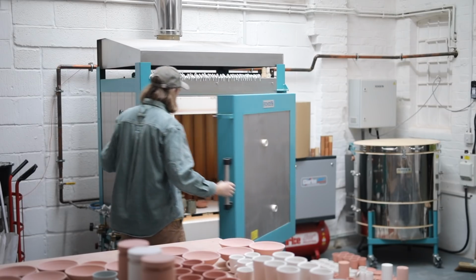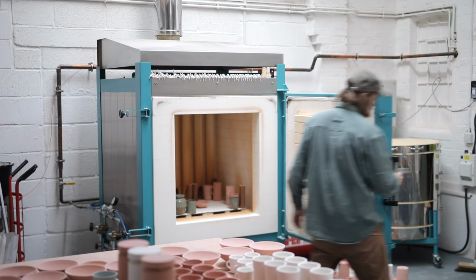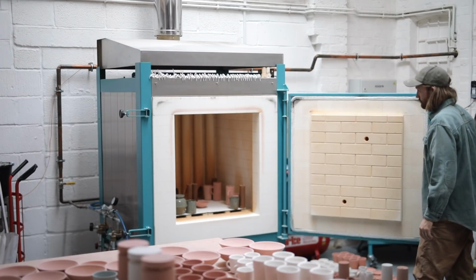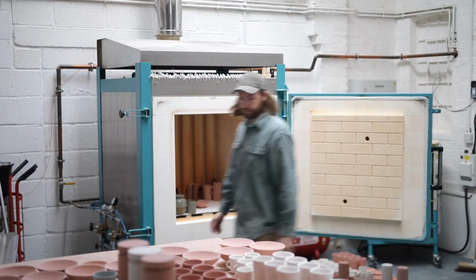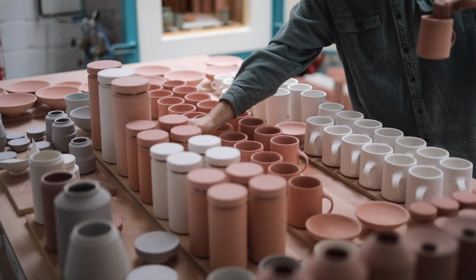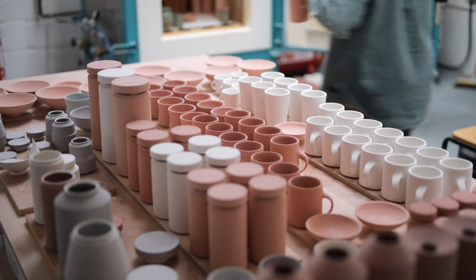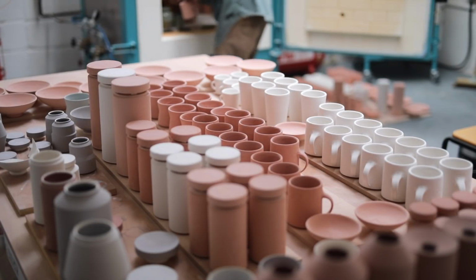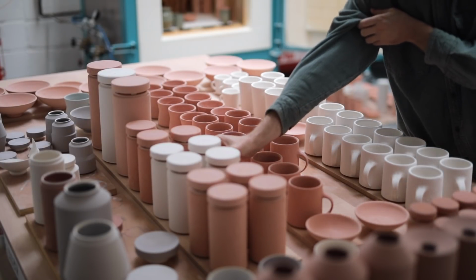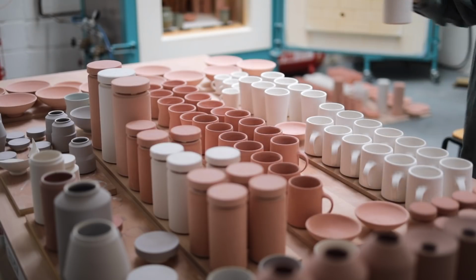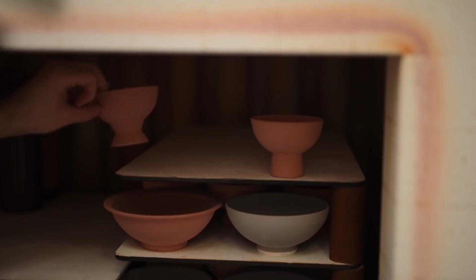My gas kiln is a Rohde HMT500, which has an internal capacity of 340 litres, which is 12 cubic feet, and I can squeeze about 150 to 170 pots in, depending on the size of course. Whilst for their bisque firing I could pack the pots so they touched one another, for a glaze firing like this they absolutely can't touch, otherwise the glazes from each of them will fuse together and the pots will usually be ruined, so as they go in they're positioned with about 2 to 3 millimeters between them.